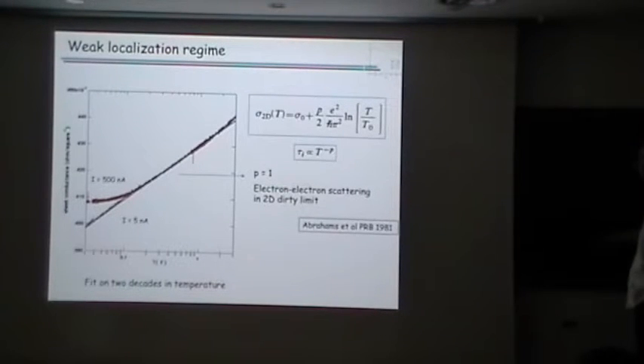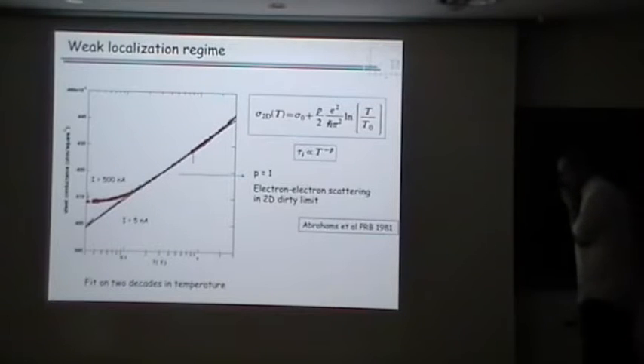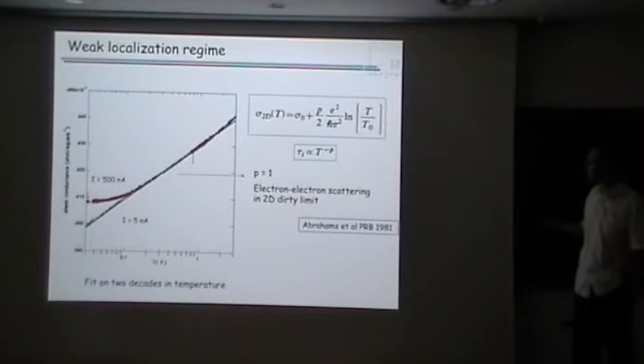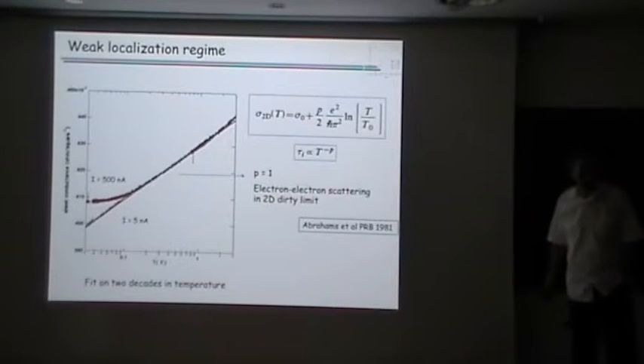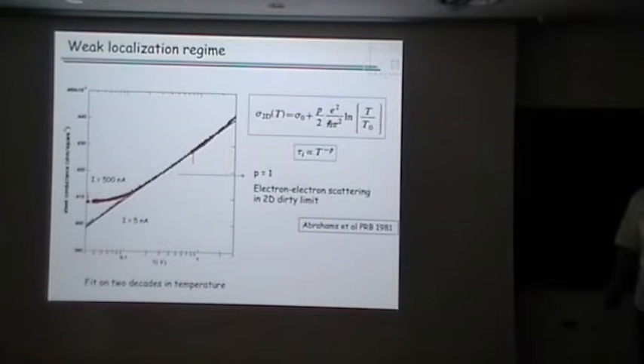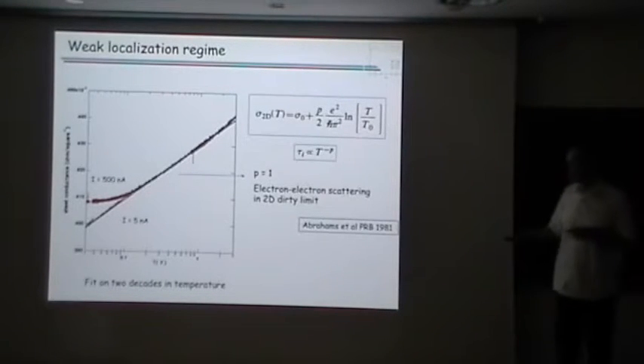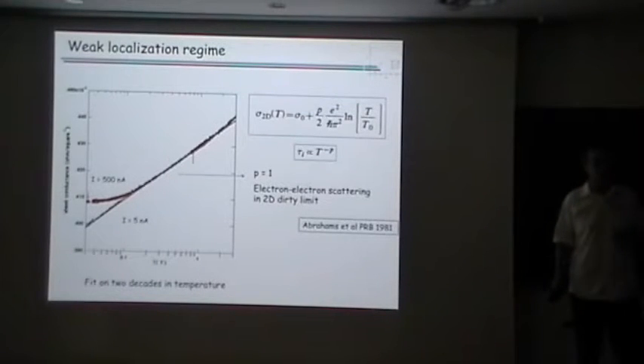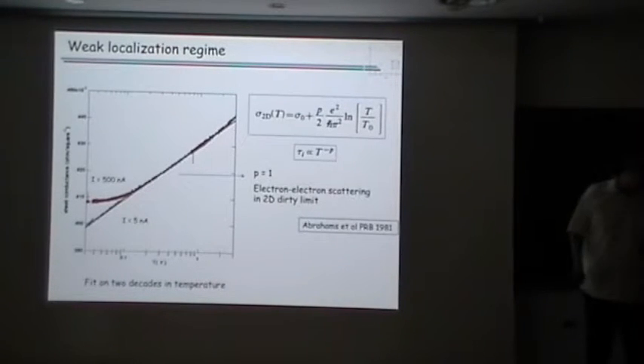If we look carefully, these are 2 decades of temperature from 30 millikelvin to 3 Kelvin, and you see we have a perfect agreement between the data and just the weak localization behavior for the conductivity. The exponent here tells you that the main inelastic scattering process is electron-electron scattering in the 2D dirty limit, which is exactly what you expected. I just mentioned that if you put too much current, you have a saturation. I mention this because in some papers people claim there is special stuff here, some kind of quantum behavior and so on. It's just trivial.